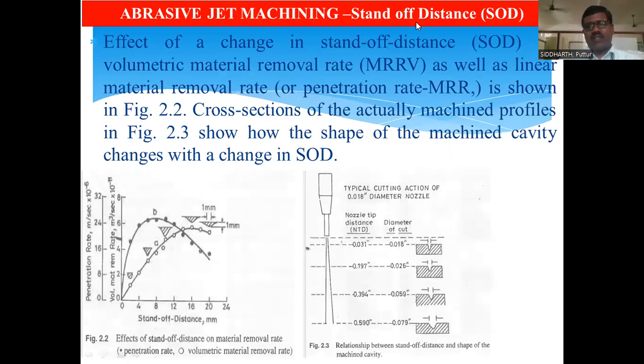Now coming to the effect of standoff distance on metal removal rate and surface finish. The effect of change in standoff distance on the metal removal rate as well as linear metal removal rate is shown in figure 2.2. See here, the standoff distance is on the x-axis, and metal removal rate and penetration rate are on the y-axis. When the standoff distance increases from 0 to 12, the metal removal rate also increases accordingly. If you still increase the standoff distance from 12 to 24 mm, the distance between the tool, that is the nozzle, and the workpiece increases, the effect of the abrasive particles is reduced, so the metal removal rate is going to reduce.